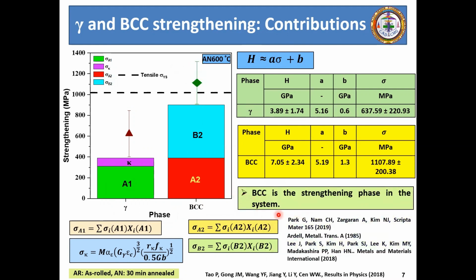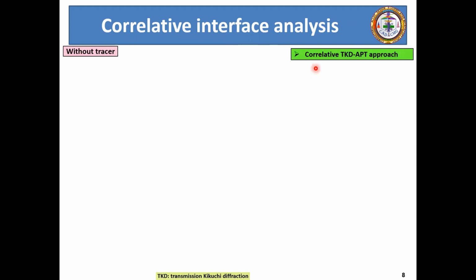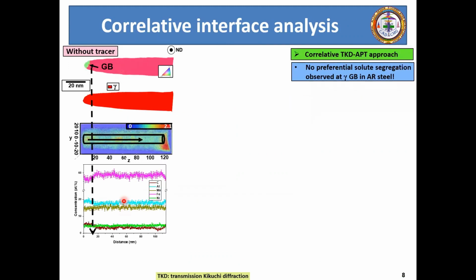Now, what about the strengthening at the interfaces then? For that, we have embarked upon correlative interface analysis at a near atomic scale using the correlative TKD-APT approach, initially without tracer addition, where from the correlative analysis, we can clearly see that there is no preferential solute segregation at an FCC grain boundary.